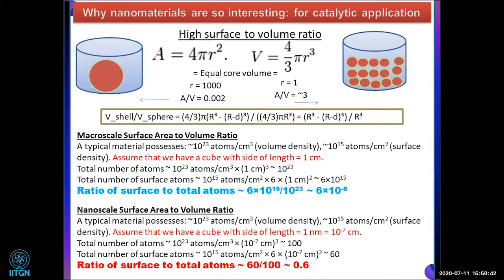We always say nanoparticles have very high surface area. So how is it actually helping? Say we take a bigger ball of radius r equal to 1000, and an equivalent, say we make 1000 balls of radius equal to 1. This is for the calculation. If we calculate the area and the volume for both and take the ratio, for the bigger ball we get A by V of 0.002, and for the smaller balls we get A by V of 3. That means for the same material, if it is a smaller ball, that is r equal to 1, you can see the area to volume ratio is much higher than the bigger one.